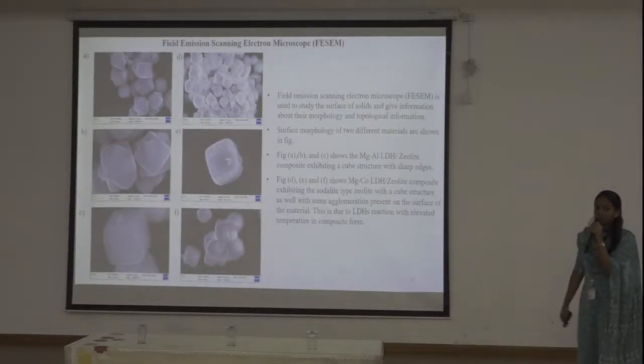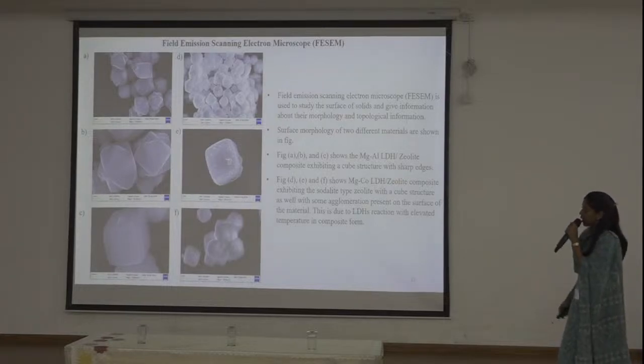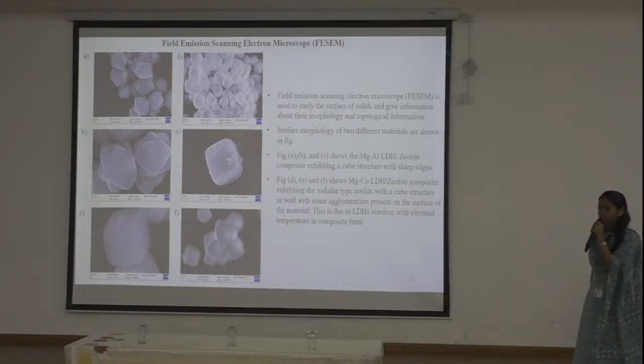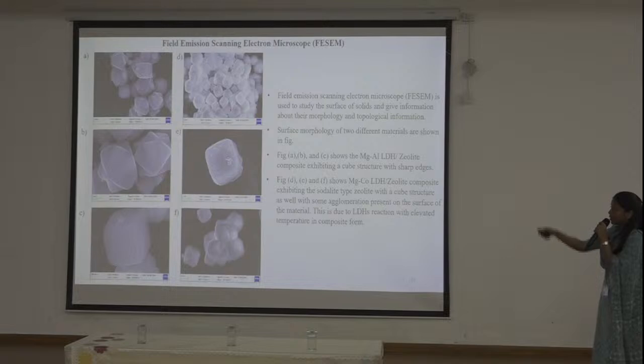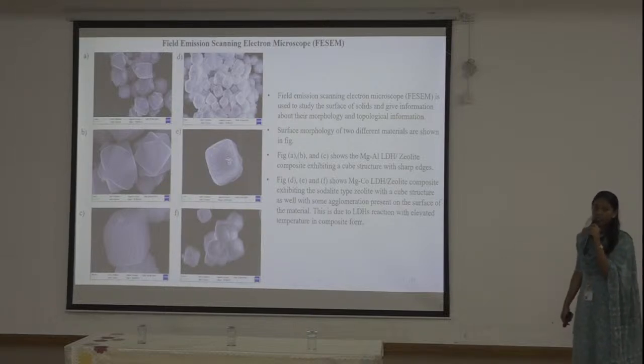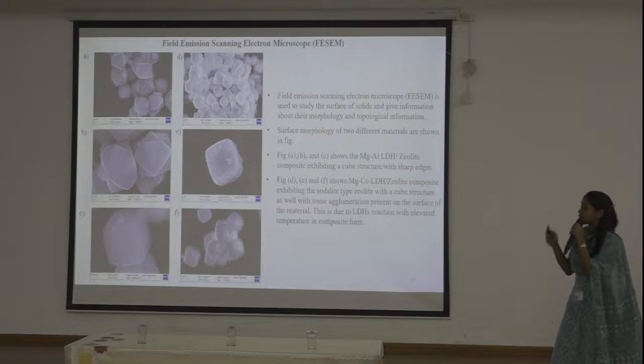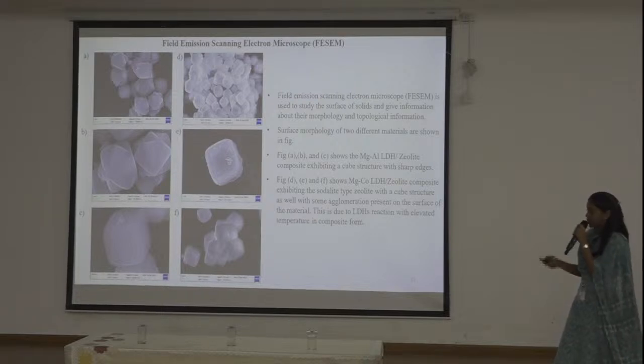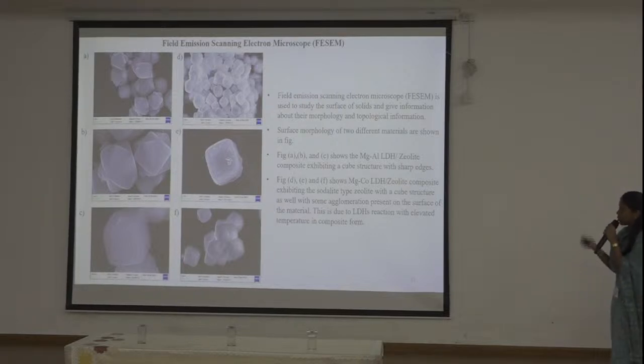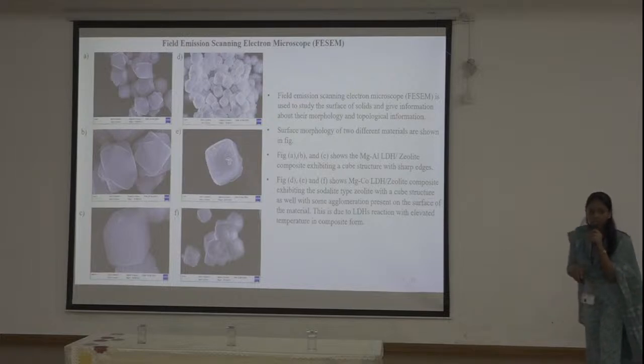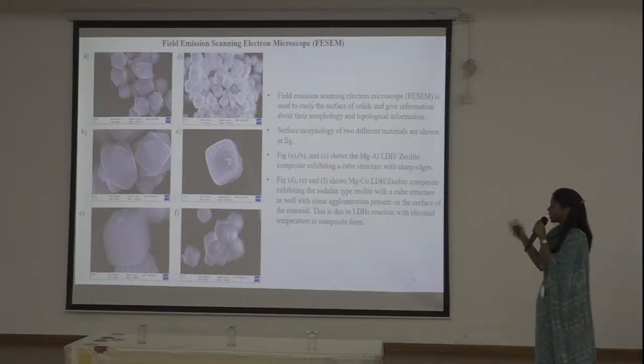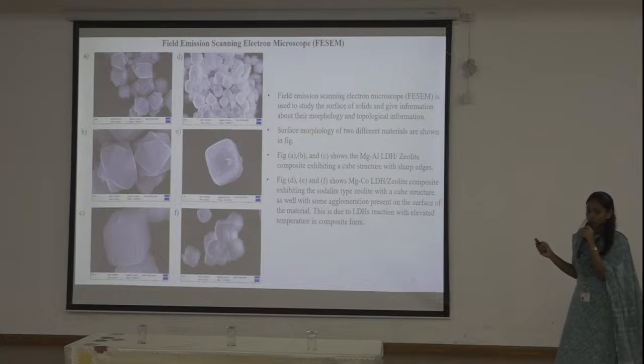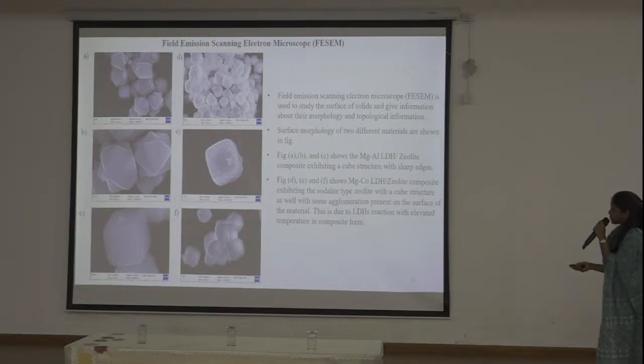We tailored the surface morphology and studied it through FESEM, where A, B, and C show the morphology of magnesium aluminum LDH zeolite, with its unique cube-like structure with sharp edges. The tailored morphology of magnesium cobalt showed a new type of zeolite structure, a sodalite-type structure with some agglomeration on the surface, possibly due to the inclusion of LDH dopants.